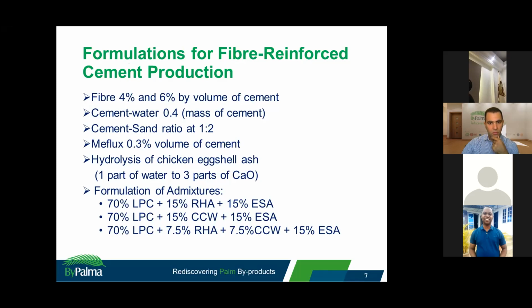What Meflux does is create a good surface area of bonding for our raw materials, whereby, in plain terms, it reduces the quantity of water you need for the mixture. So I used Meflux at 0.3% of the total volume of the cement used for the experiment. That's why we introduce 0.3% of Meflux, so that we will not change our water-cement ratio from the initial one used for the wet carbonation.